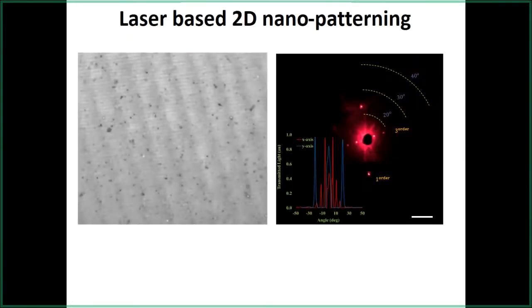This is just to show you the flexibility: with this sort of setup, you can make very high aspect ratio samples as well. So in one direction, there is sub-micron periodicity, and in the other direction, you have micron scale periodicity. If you're using photolithography, or you're using electron beam, this turns out to be a slow process for samples like these. So in one direction, a very small periodicity, and in the other direction, very large periodicity. You can see the anisotropic asymmetric diffraction pattern over here.